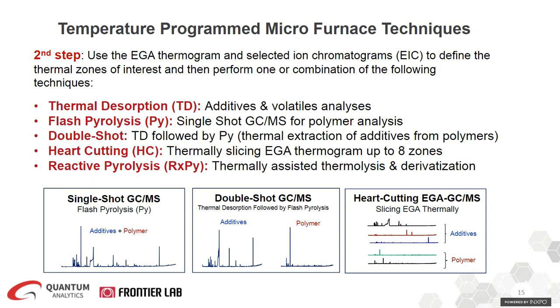But as we discussed, if you have some additives and if you want to identify them, now you could do a double-shot GCMS. We call this a double shot shown in the middle because this is two analyses on one single sample. First, you thermally extract the GCMS chromatogram. We call it a thermal desorption chromatogram. And then the second shot or the second analysis is to perform a flash pyrolysis. And you obtain a separate GCMS chromatogram. We call it a pyrogram to identify the heavier and the polymeric components.